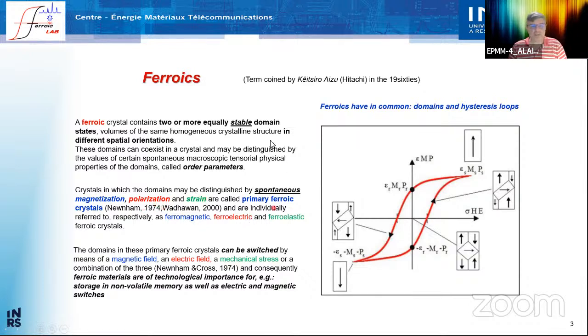This property can be inverse. The order parameter can be switched by the means of the conjugated field. The magnetic field switches the magnetization, the electric field the dielectric polarization, and the mechanical stress would switch the strain. And ferroics are therefore characterized by the presence of domains and by the presence of a hysteresis loop when you sweep the conjugated field from negative value to a positive value, and you switch the domain. So here all the domains are in this state, then you have the remnant polarization or magnetization or strain at zero field, and then you go to the inverse and you come back.